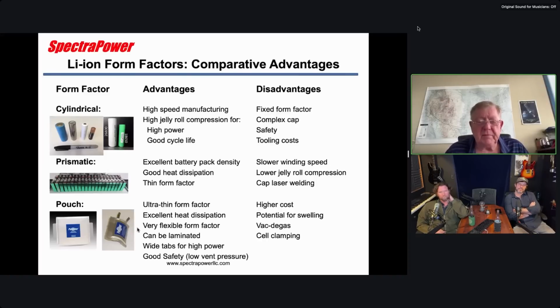And then for safety, I think they're about the best, because the pouch will vent typically somewhere less than 100 psi. It'll start to vent. So instead of like a cylindrical, which if it plugs up, it can go up to 1,000 psi before it explodes, this will vent. You still have some of the safety issues, but not as violently. Disadvantages: it's more expensive. It can swell if you have problems. It'll puff up like a balloon, and you have to do what's called vacuum degassing when you're manufacturing to suck all the gas out of it. So that adds cost. And like I said, you may have to clamp it to keep it from compressing, depending on what kind of technology.